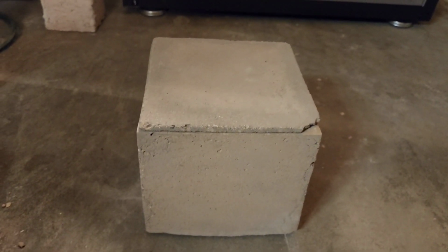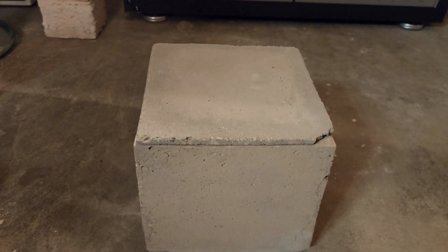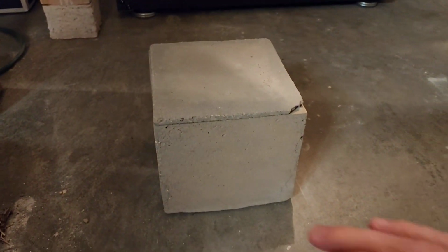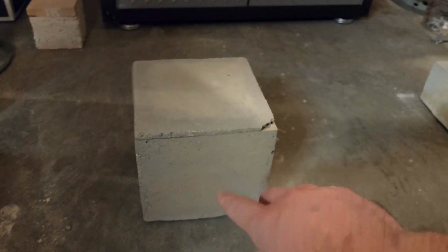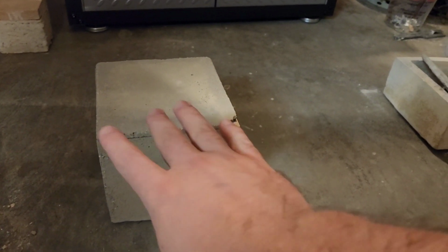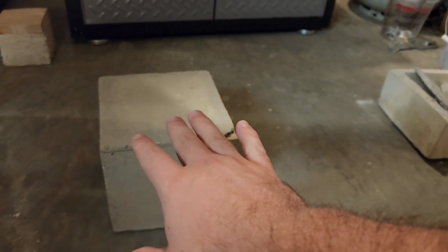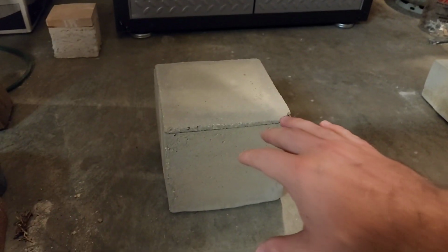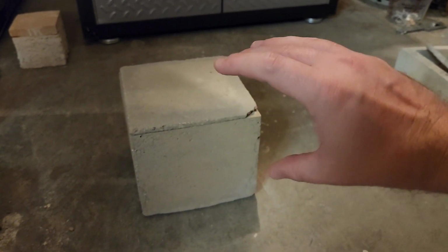Anyway, so what we're going to do is zap this for another 20 minutes, I think, and see if we hit some critical limit. Okay, sad day. Well, we did what we could, but after 90 minutes in the 1100 watt microwave, we did max out. The final resting temperature of the internals was around 878 degrees Fahrenheit. This was decreased from the peak of 910, which we achieved at around the 70-minute mark.